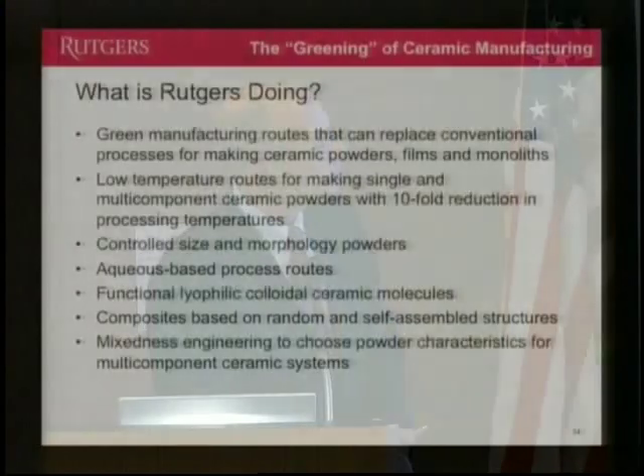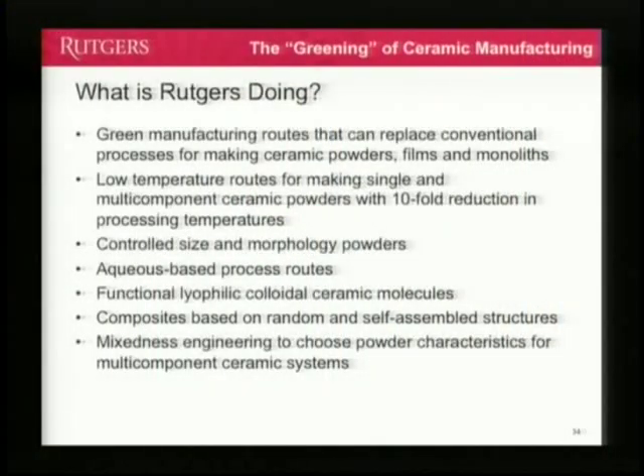Okay, so that aside, what are we actually doing? We're working on techniques that use low-temperature processes for making ceramic powders. And we can boast typically tenfold reductions in processing temperatures. And by controlling the size and morphology, we avoid the need for milling, so we no longer have to grind things. We use water-based routes so that we can recover the water. In fact, we precipitate these things from aqueous solutions, which leaves you with clean water afterwards.